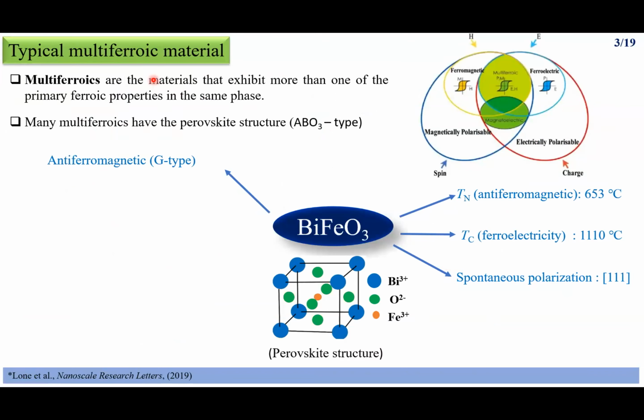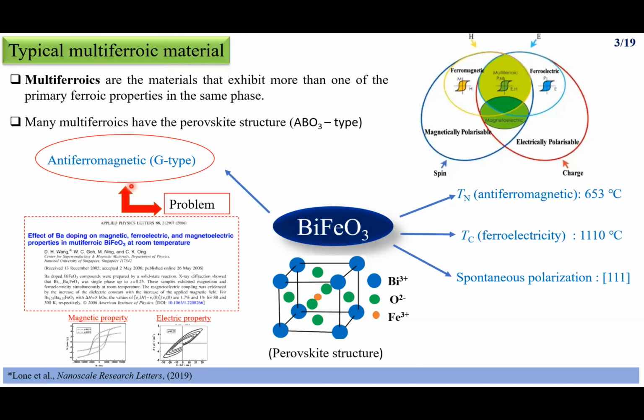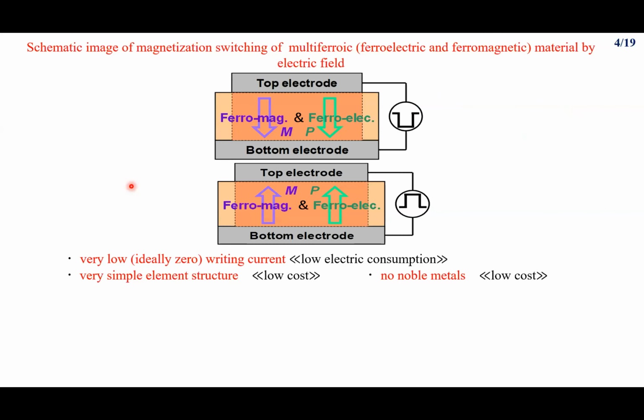So let's think about one idea, that is multiferroic material. As we know, multiferroic materials exhibit more than one ferroic property in one phase, and these are mostly perovskite structures. Here I'll be considering the bismuth ferrite perovskite structure because it has spontaneous polarization along the diagonal, and here I will not be worried about the temperature because it shows ferroelectricity and ferromagnetism at room temperature. One problem is that it has an antiferromagnetic G-type structure. But by substituting some proper elements, we can enhance its magnetic property as well as electric property.